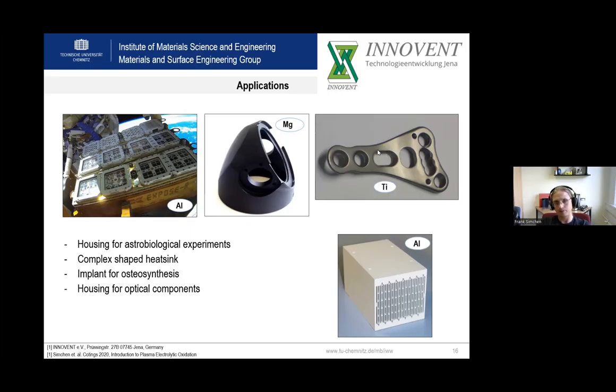Here we have a medical device which is placed in your body to repair a bone fracture. This titanium component is provided with a titanium oxide layer through PEO in order to prevent cold welding. When you apply a titanium screw inside, these components can get cold welding over time in your body. And when you want to disconnect these components, it's not so easy to disconnect the screw. That's why it's good to have a thick titanium oxide layer.